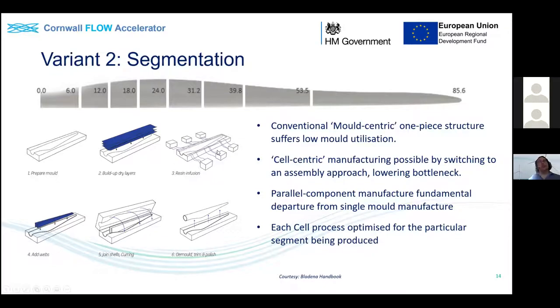You can appreciate that the steps taken for the dry fiber preforming to build up the structures prior to infusion take quite a long time, and then the mold itself is used as the assembly step to place the vertical shear webs in, which is in panel number four. And then those two shells are closed and then cured to cure off the adhesive, which adjoins those two half shells before final demolding. So it's not a very efficient way to use a piece of tooling.